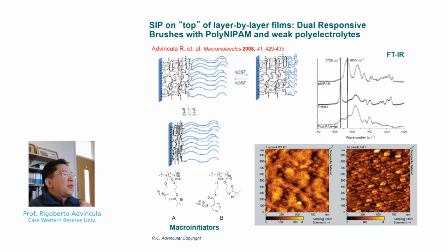Okay, here's an example of what we call a dual responsive polymer brush. The stimuli responsiveness can come from either changing the pH or changing the temperature through the LCST behavior. Hence, to do this, we would need a weak polyelectrolyte interface and an LCST behaving polymer brush, in this case, which can be fulfilled by grafting poly-NiPAM. So the polyelectrolyte layers were first deposited with the pH responsiveness of polyacrylic acid and PEI, negatively and positively charged. But the last layer actually involved the grafting of these two ATRP initiators, a positive and a negatively charged initiator.